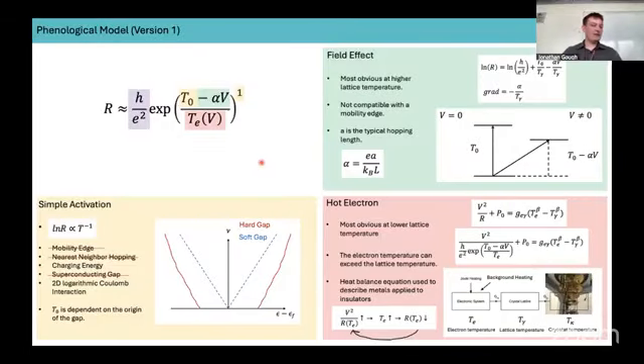So to explain our observations made in our disordered indium antimonide thin films, we use this simple phenomenological model, where we assume a prefactor close to the quantized value, h upon e squared. We know we're in this simple activation regime, hence this p value is 1. So simple activation can be due to a variety of reasons. Most famously, a mobility edge. Any sort of gap in your density of states can lead to this effect.